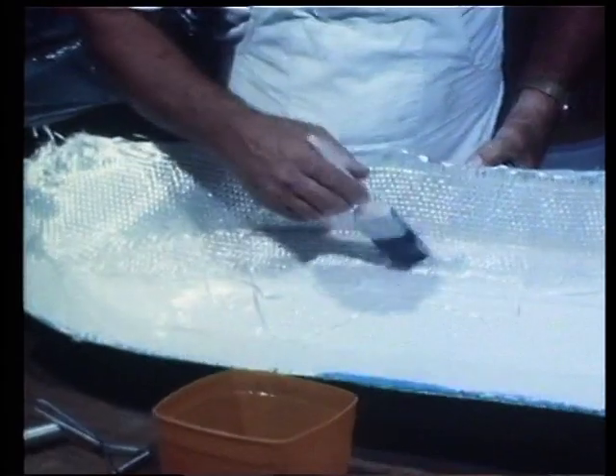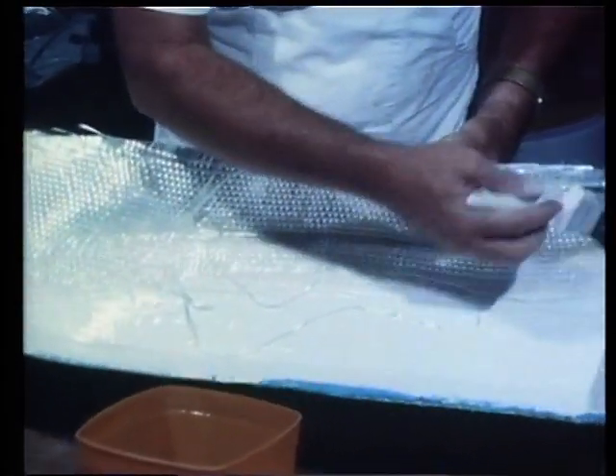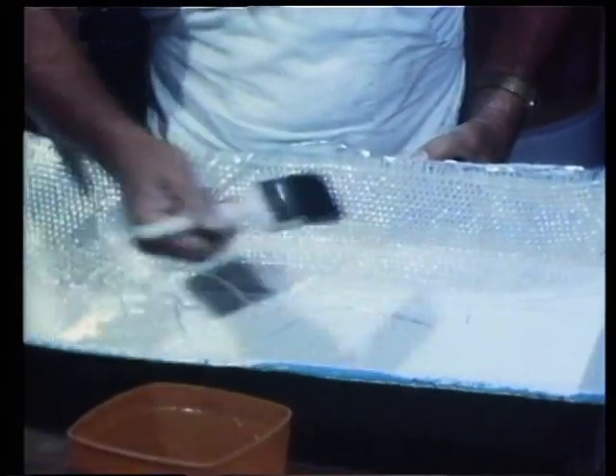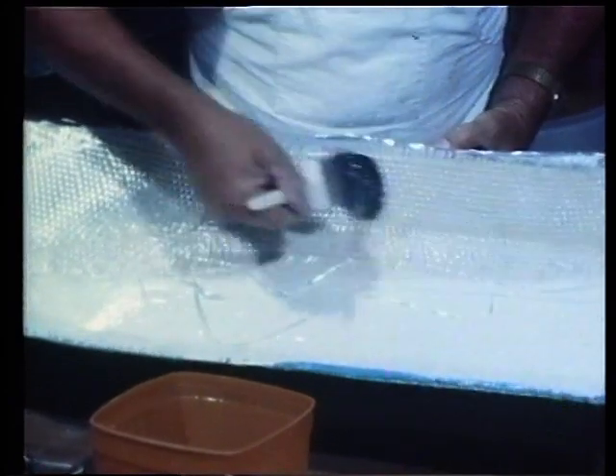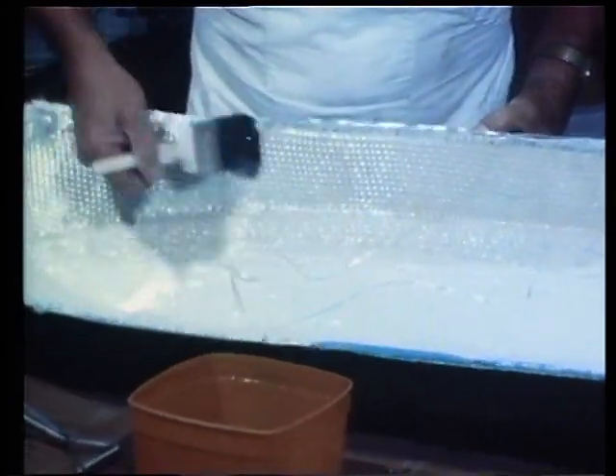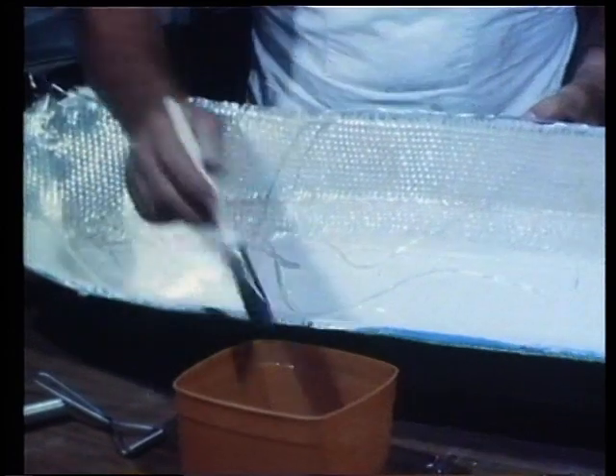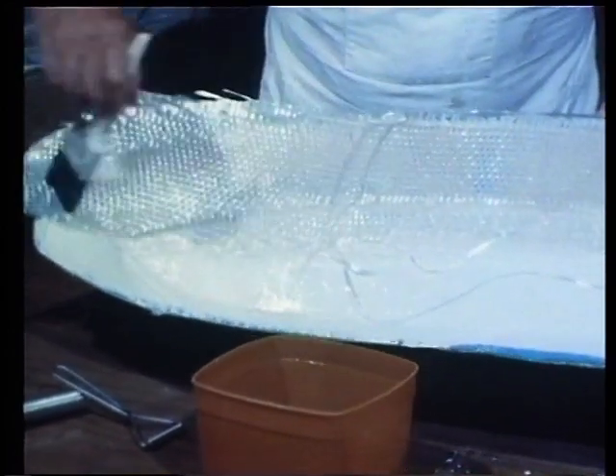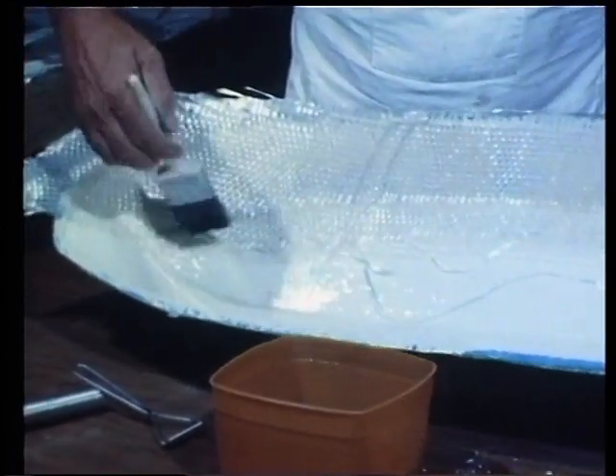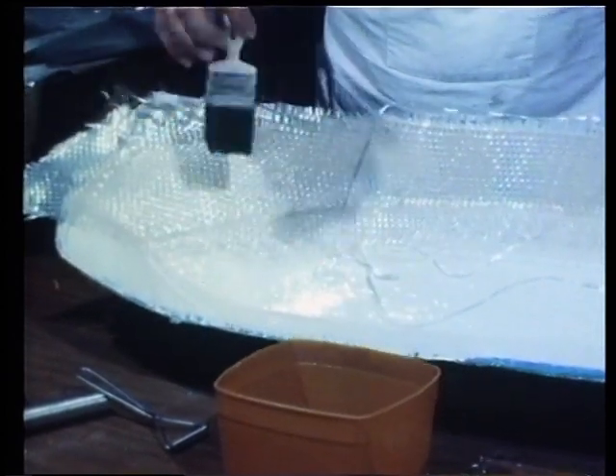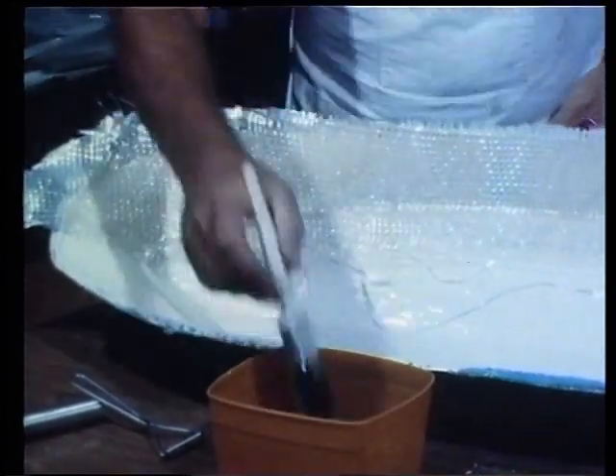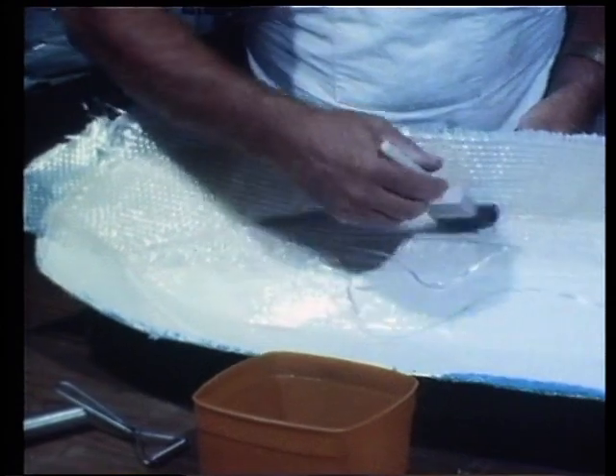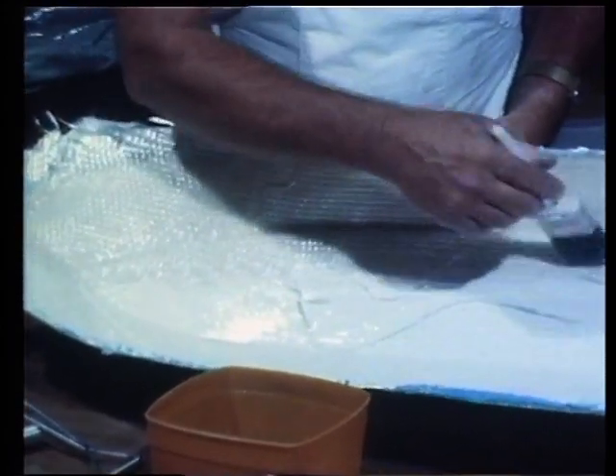Now that, again, you are aiming to minimise the amount of resin that you put into the mould, along with making sure, of course, that it's properly wet out. Now with woven roving, because it is a fairly tight weave, it's possible to brush the resin in rather than having to stick completely with that stippling action. But the stippling action not only is used to govern the amount of resin you put in, but it's also used to control and move the glass around.